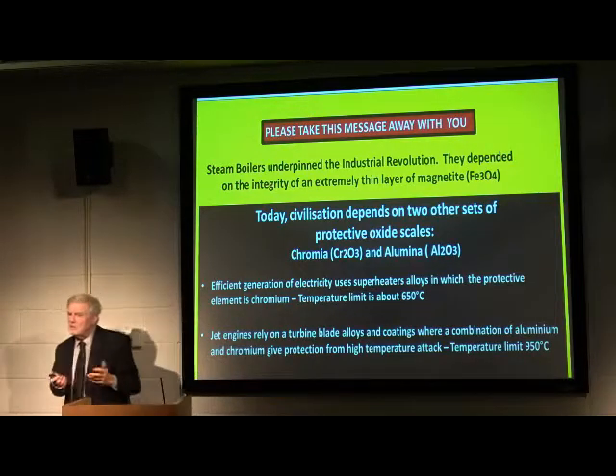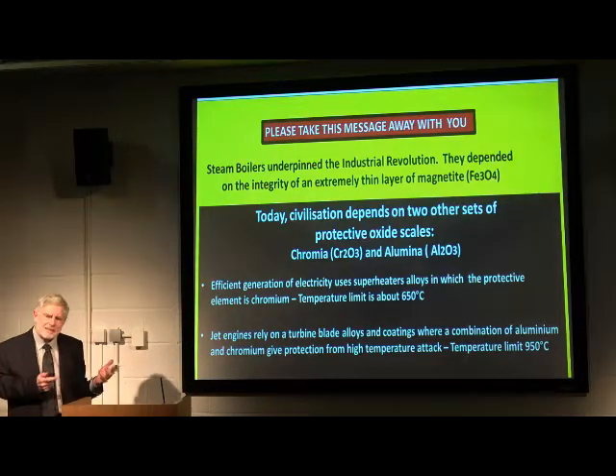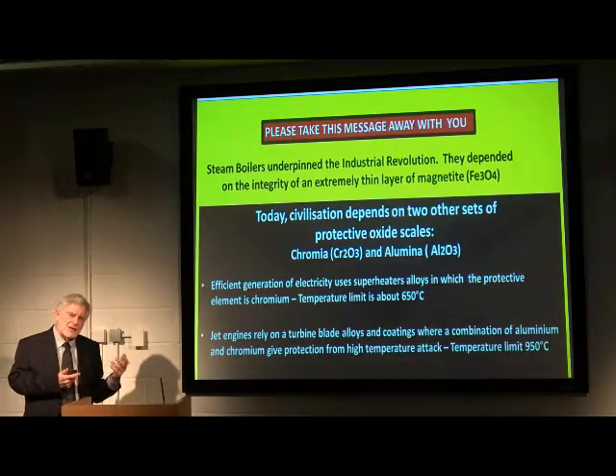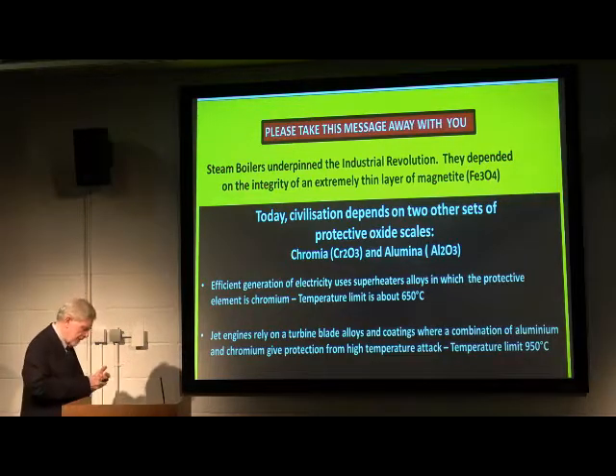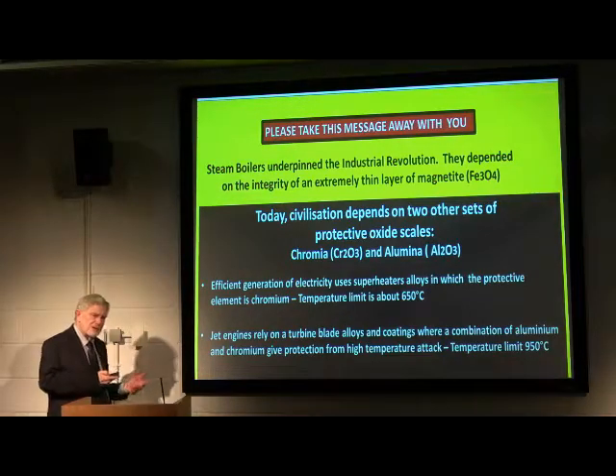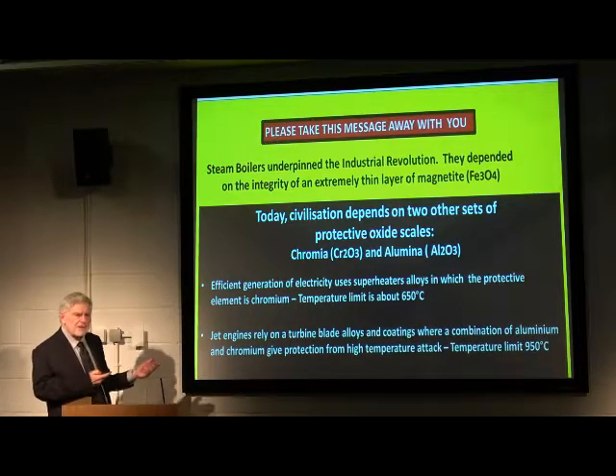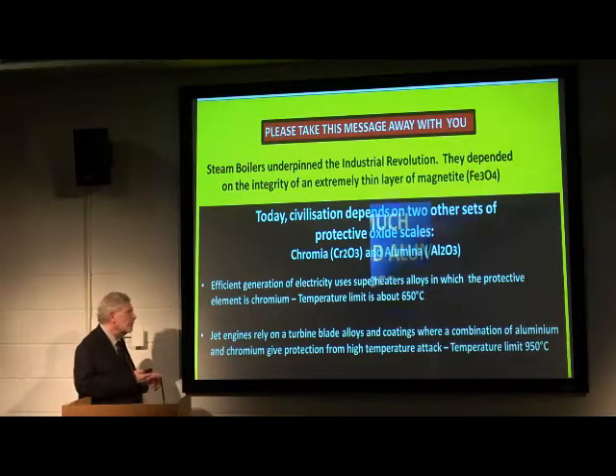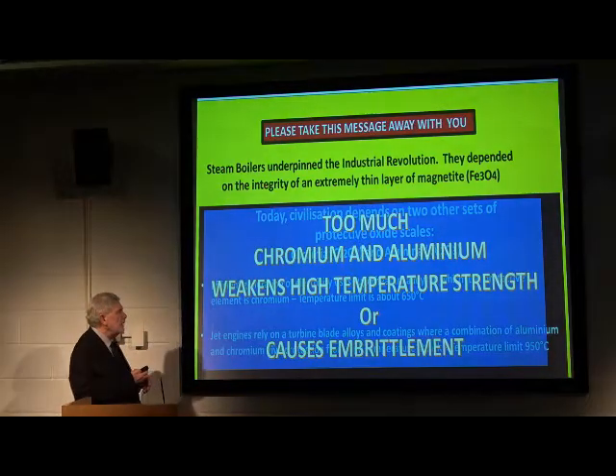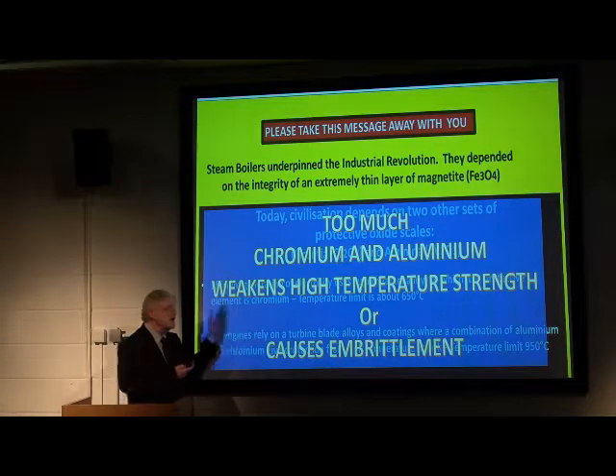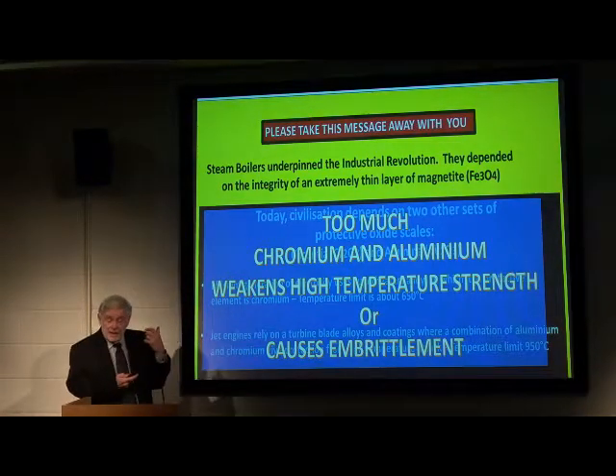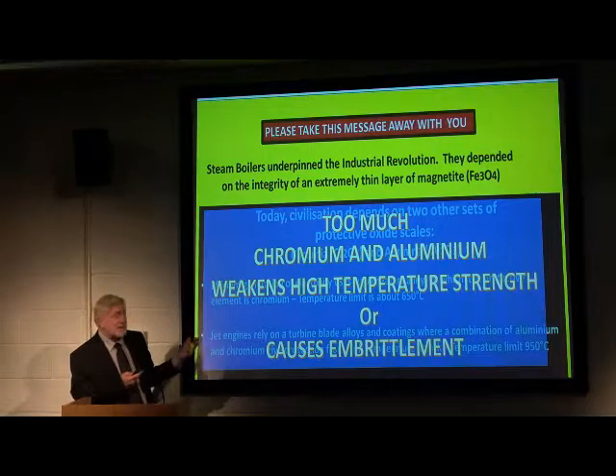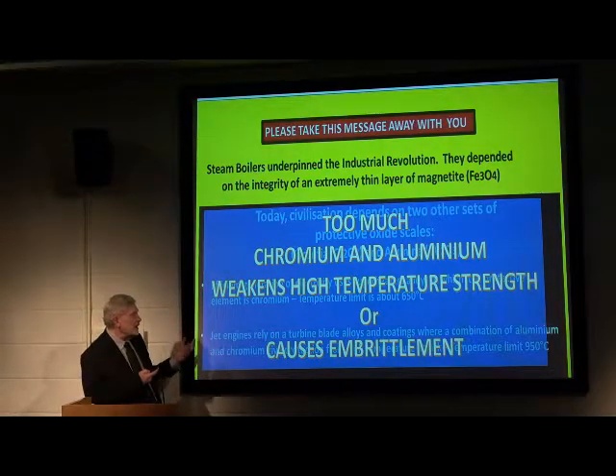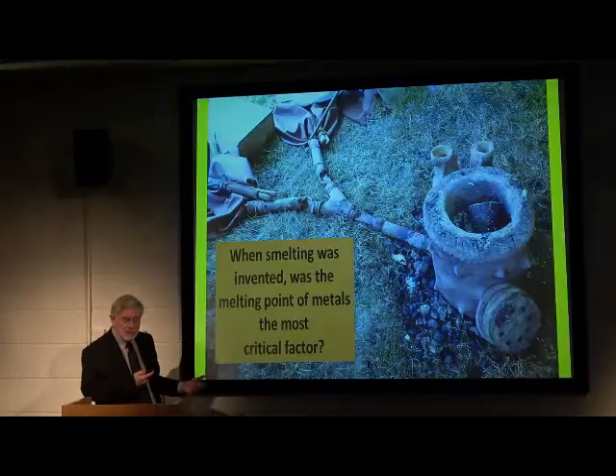If you look at that Rolls-Royce alloy, which has been used in the Trent, it is really quite marginal, in my view. Not enough chromium. Certainly not enough chromium. And really, I think the aluminium level is quite low. If you try and push up the chromium and aluminium contents, it weakens these materials. You get the wrong kind of phases, as they're called, or it will cause embrittlement.